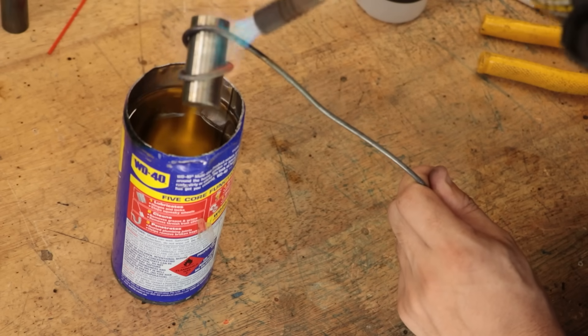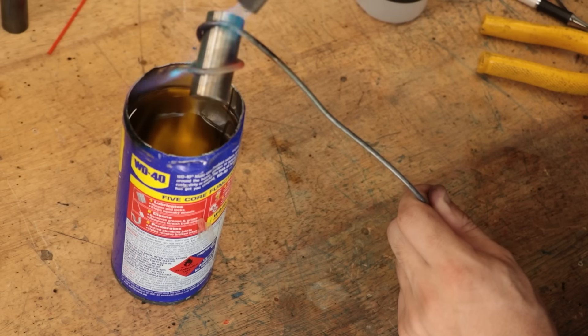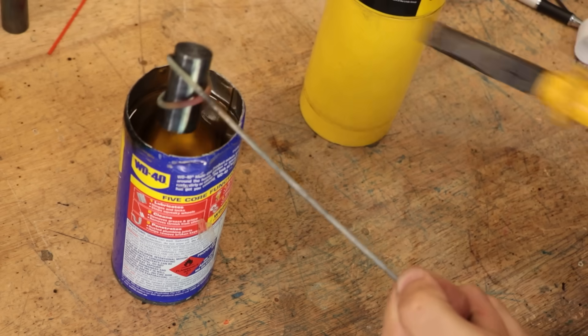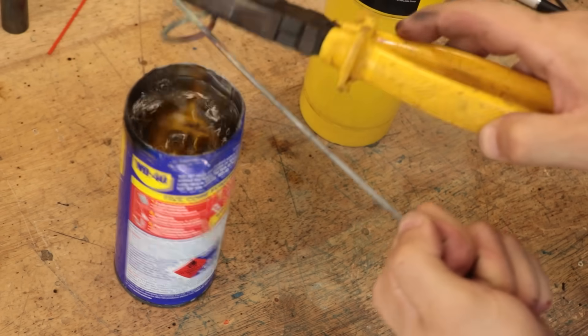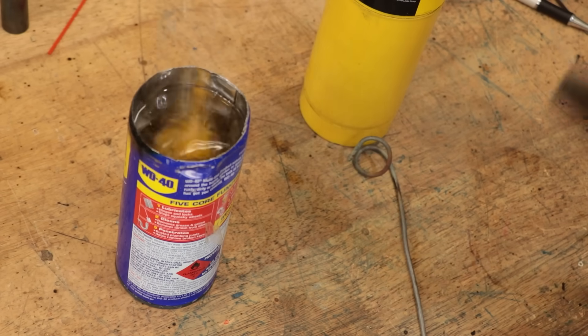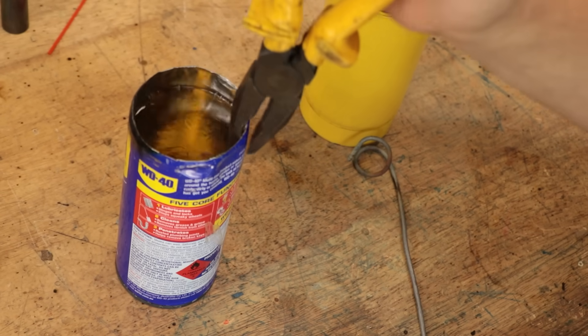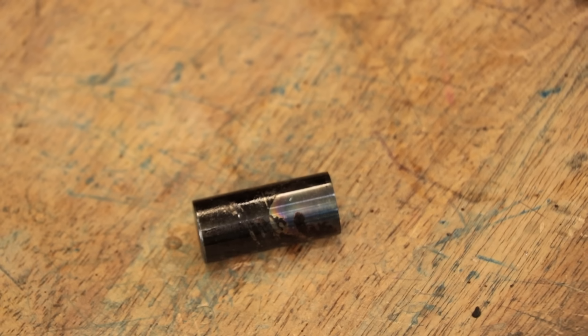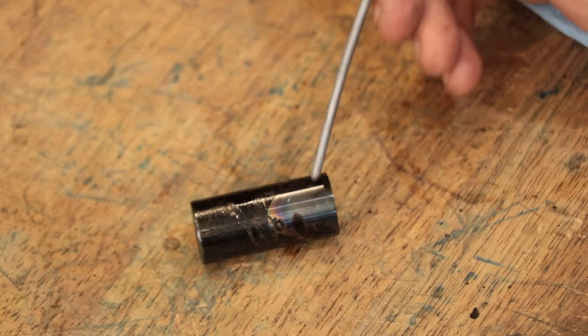The only bit of skill in doing this is making sure the part has even heat coverage and making sure it's at the correct temperature before you dunk it. If the part's too cold, this simply won't work, and if the part is too hot, I find it simply burns up any oil and becomes sticky.